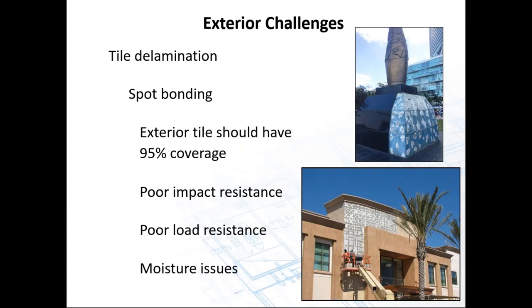So what we're looking at here is a tile delamination. These pictures show what was done on this installation of a spot bonding. In other words, the installer took globs of mortar, placed it onto the wall, onto the tile, and just pushed it into the wall, getting a nice flat wall, look great on the finished application, nice and smooth. But as the project went through heat and cold cycles, the tile started popping off because there wasn't adequate coverage onto the back of this stone.